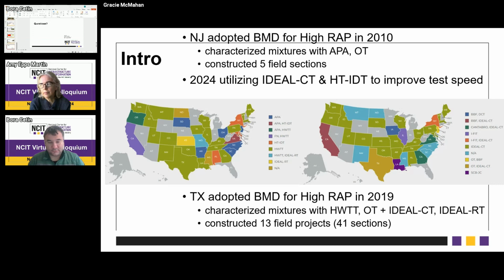And they have 5 field sections that this project is monitoring and taking cores on and determining how those mixture properties evolve with time. In 2024, they started adopting a monotonic, more practical test that might be able to be utilized during production of these high RAP mixtures. And that's the IDEAL cracking test and the high temperature indirect tension test. And the idea there is to be able to make sure that what's being produced and put down in the field still has the balance of cracking and rutting resistance.